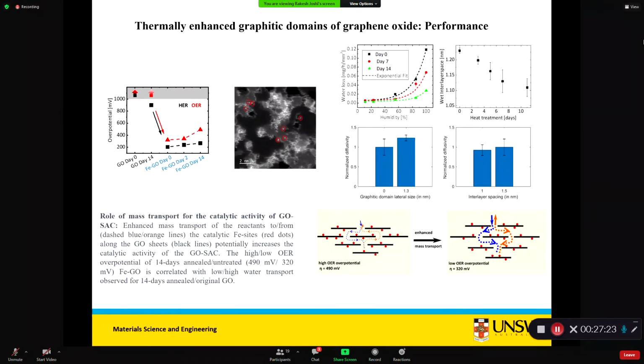And so then we did a simulation study, because in principle it should be higher water flux when we have large graphitic domains. Then when we did simulation and some theory, it suggested that the water transport is governed by two things: the water diffusibility or the graphitic domain. And because when we are reducing it, you see here the interlayer space is also decreased. So now what is happening here, when we are heating it for a longer time, see the 10 days one, the interlayer space is also going down, right?